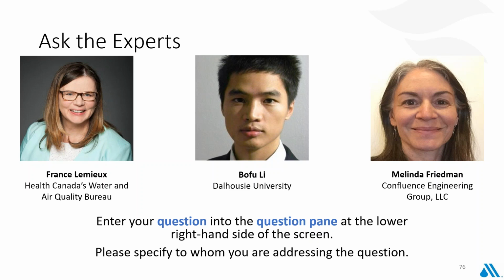And I wouldn't suggest that it would be useful as a replacement of lead sampling itself. I think it's a good indicator that there may be lead present, because, as Bofu indicated, lead does get absorbed by the iron. So in terms of iron, it goes back to the principle that if you've got iron in your water, then you may have lead as well, and it may be a useful indicator, but it certainly wouldn't be something that I would recommend sampling for instead of sampling for lead. As Melinda indicated, there are a number of tools you should be using, and that could be one of them as well.